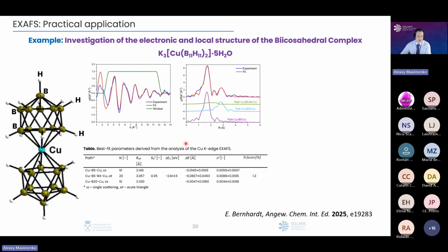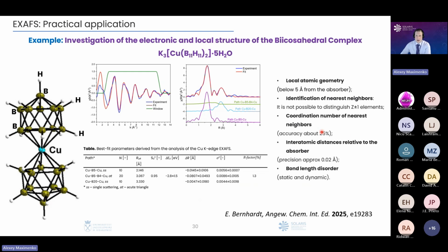So in such a way, we could prove whether the model which we have for our compound is true or not. And that's how, once again, you could see what kind of information we could get from EXAFS measurements. Once again, local atomic geometry, but definitely here you could see what kind of limits we have. Identification of near neighbors, what kind of atoms we have around, how many of them we have, the distance between our absorbing atom and the neighboring atoms, and also what kind of disorder we have in our material.